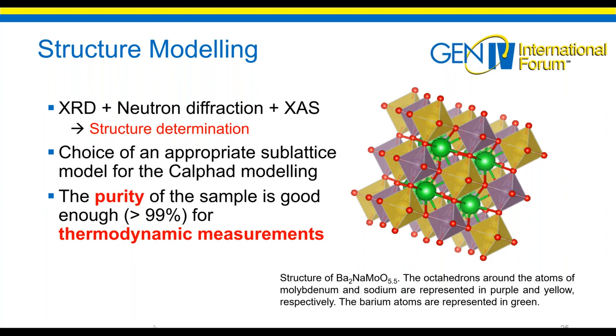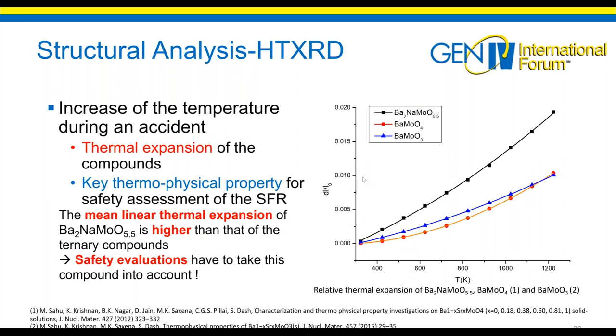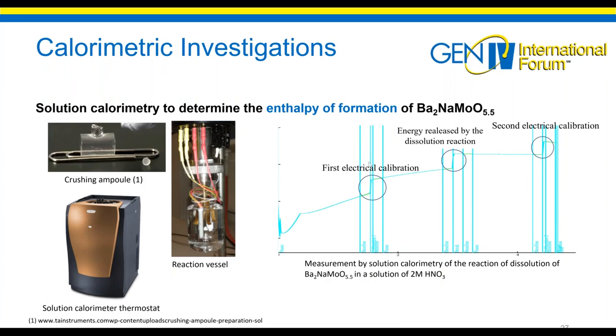And as I was saying, the purity of the sample was good enough for thermodynamic measurements, so we performed them. We performed some, but before we did some high temperature X-ray diffraction measurements.